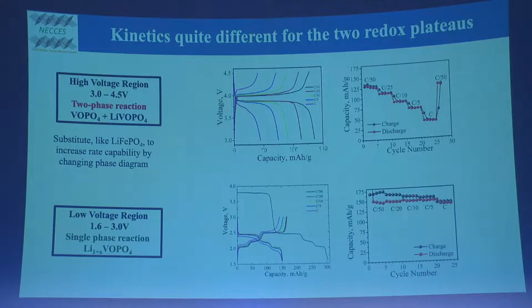You'll also notice in this region here, this is the amount of charge you're putting in, the black. The red is how much we're taking out. We're not taking out the theoretical on every count, so we're putting more charge in. So our vanadium phosphate is in fact reacting with the electrolyte. It's a very good electrocatalyst.